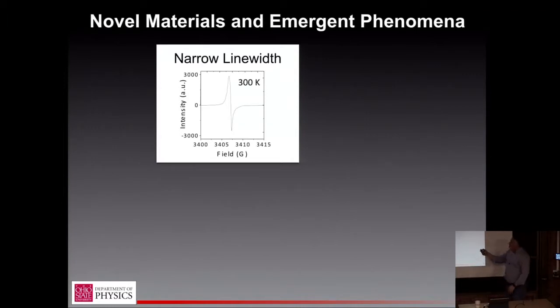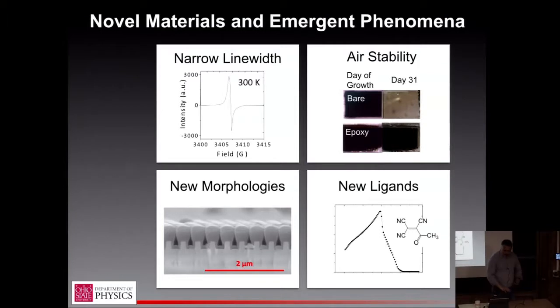So basically, building off this result, we said, okay, we think this is a really exciting material. We want to double down and move forward with it. And over the past 4 to 5 years, we've come up with a series of technical breakthroughs that we think will really allow this material to move forward in new and exciting ways. So one of the more important technical aspects is addressing the air stability. Using encapsulation techniques developed for OLEDs and OPV, we can extend the lifetime of V[TCNE]x films under ambient conditions from 30 minutes to almost a month.